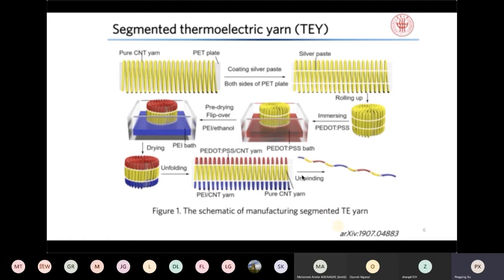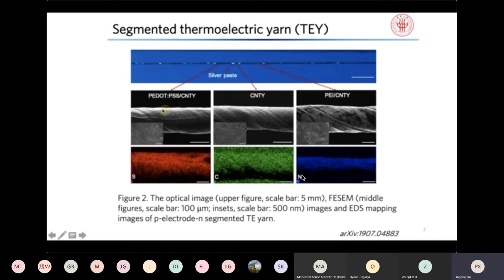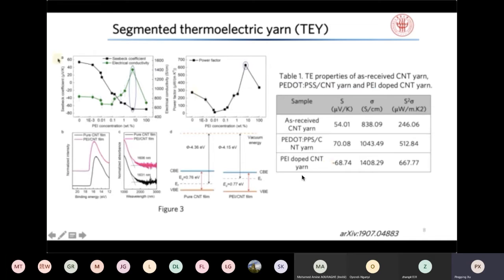And we confirm the doping of PEDOT:PSS and PEI by EDS mapping. As sulfur is a characteristic element in PEDOT:PSS, we can see that it is evenly coated. And PEI has the characteristic element nitrogen, so we can see that it is also evenly distributed along the carbon nanotube yarn. Okay, the middle part is the pure carbon nanotube yarn as the electrodes connecting the p-type and n-type materials. All right. So we also measure the thermoelectric properties of the different three segments: the connecting pure carbon nanotube yarn, the p-type one and the n-type one.